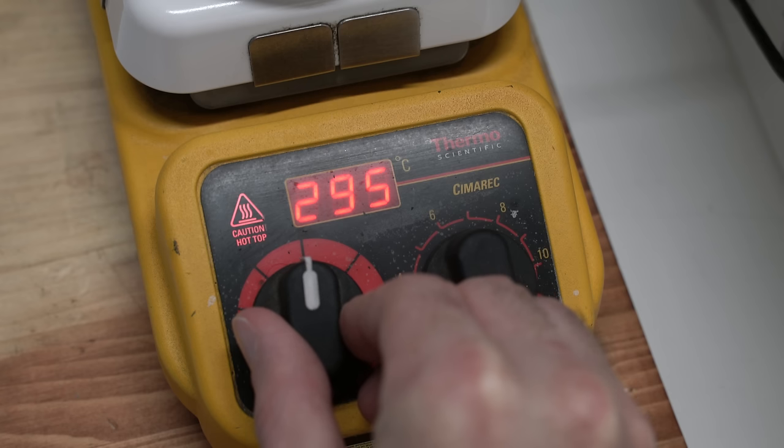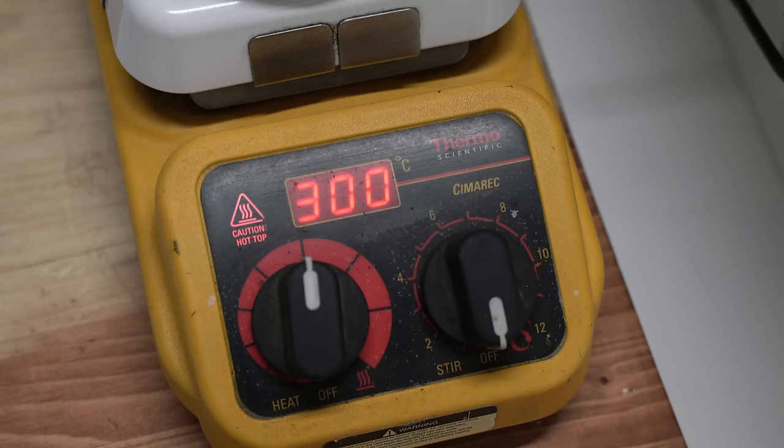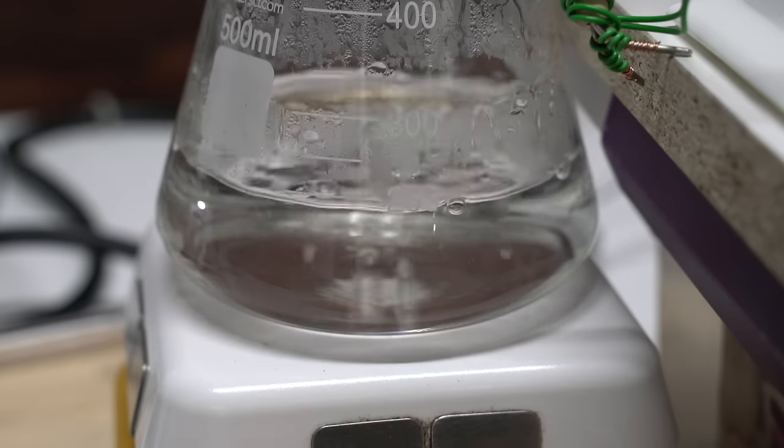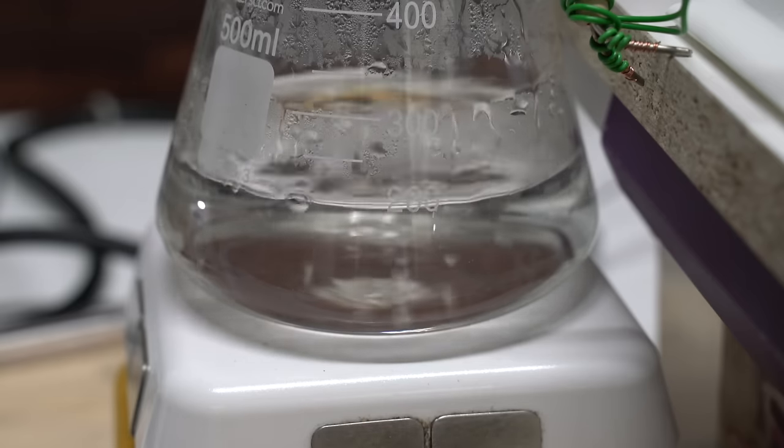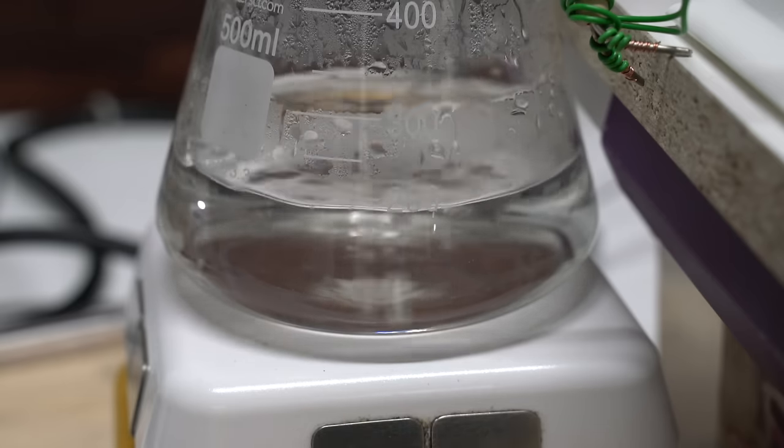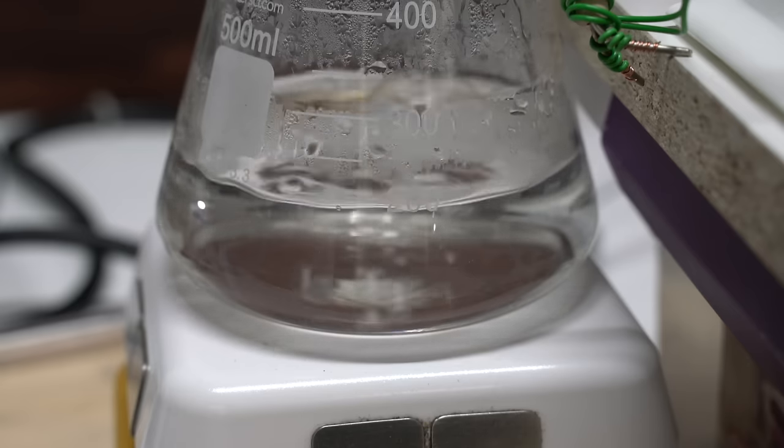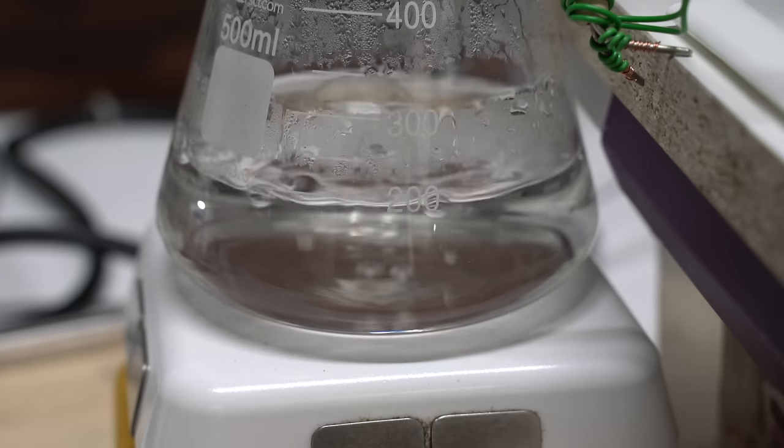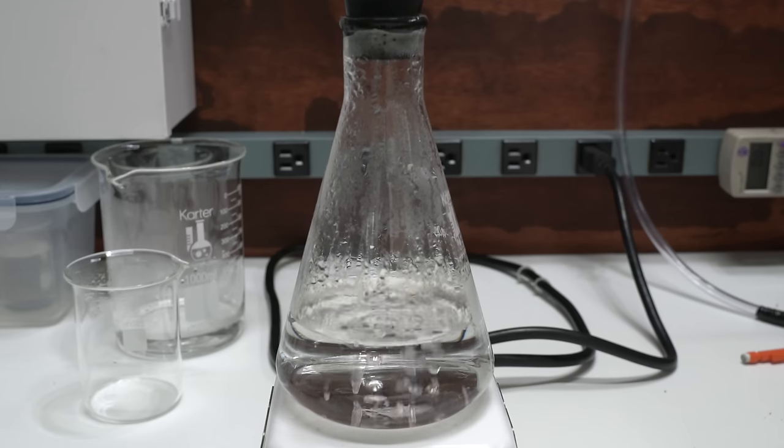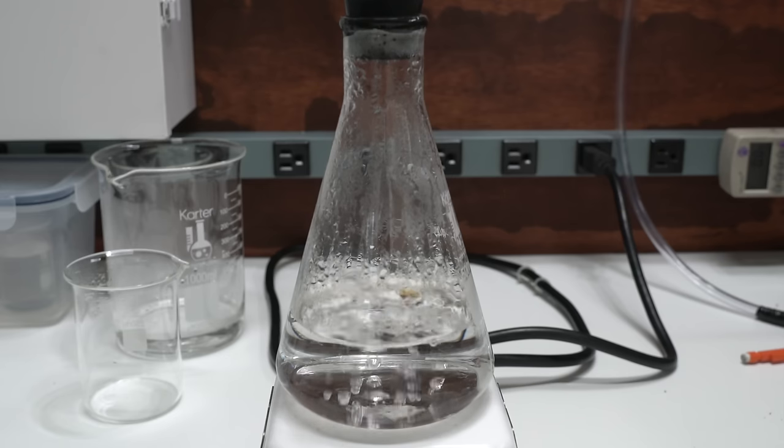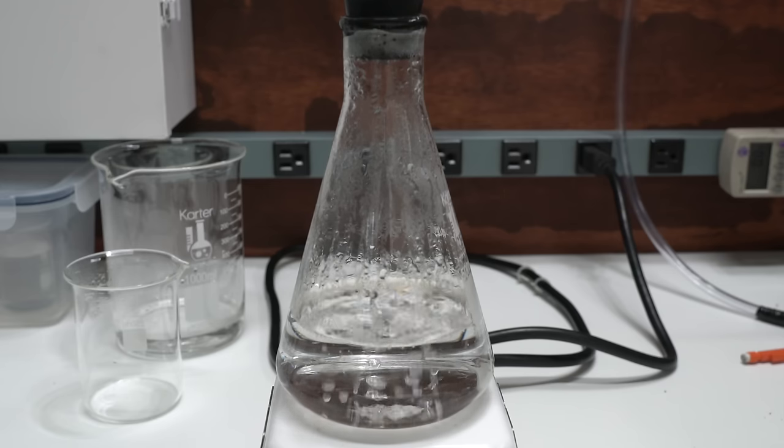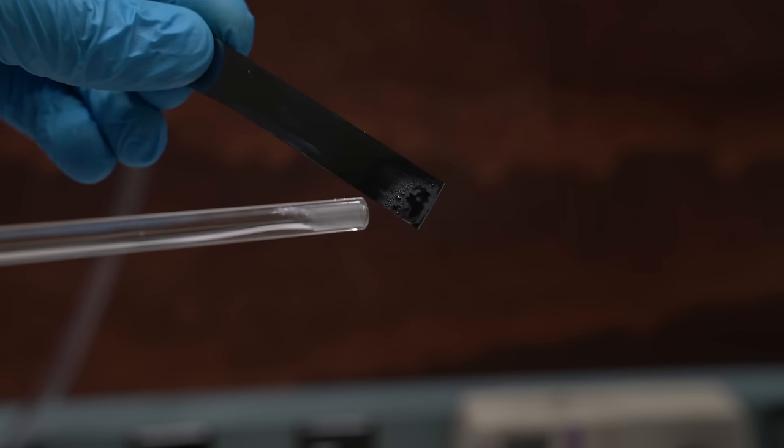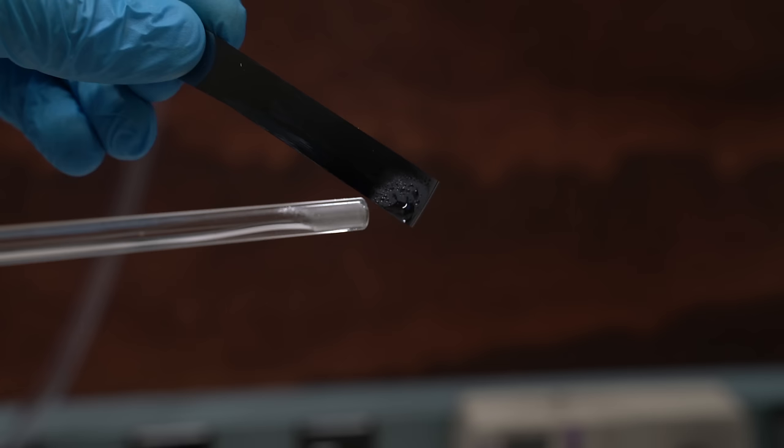I had set the hot plate to 300 celsius, which should be more than enough to boil water, but that's not really how hot plates work. 300 celsius means the temperature the hot plate will reach if nothing is on top of it. A flask of water on top prevents the temperature of the plate from going much above 100 celsius until all the water is boiled off. In that case, and for this hot plate, 300 just means medium heat. Because the heat wasn't enough, some of the water was actually condensing on the side of the flask and not exiting the steam generator. The apparatus was definitely producing some steam though, so I hadn't really worried much.